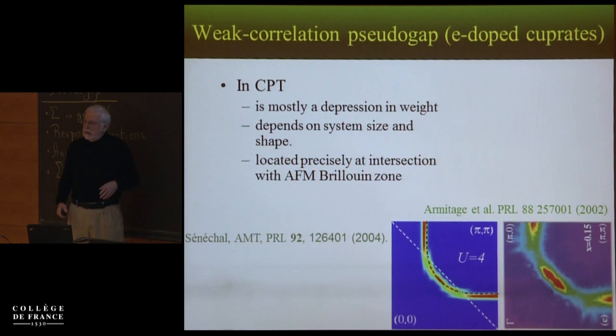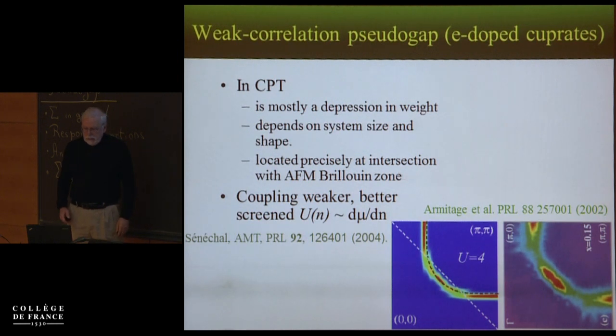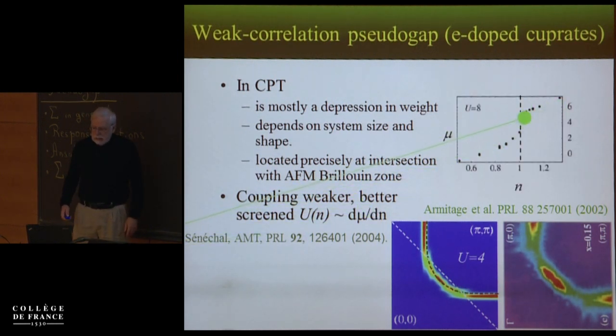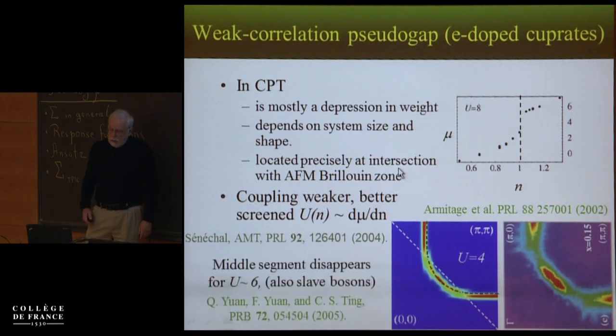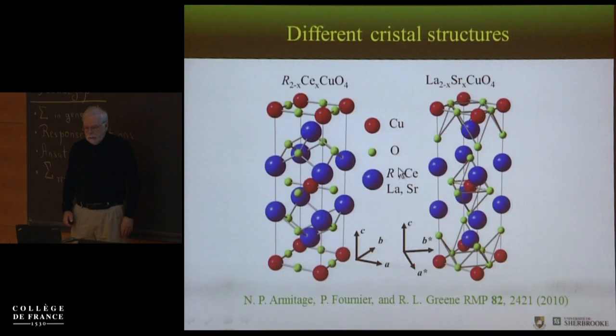So an early indication that the correlations are weaker in the electron-doped than in the hole-doped is simply that you see here U equals 4. If you take U equals 6 or more, then this piece here always disappears in cluster perturbation theory. So it's a very robust statement. There's also the fact that the optical gap is smaller, that this quantity, the d mu dn, is smaller in the electron-doped. And even in slave boson calculations at U equals 6, this piece disappears. So if you see this, it's an indication that the coupling is not so large.